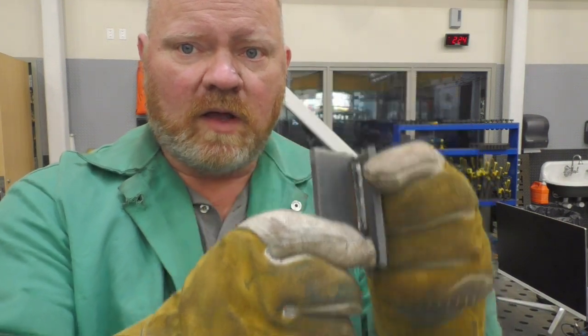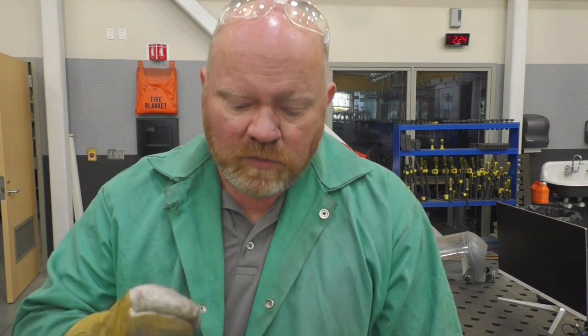And again, I also tested this on a very small weld. That's a really small weld, about an 1/8 inch fillet weld, okay? So if you're gonna plan on putting down larger welds, multiple pass or whatever, the root pass is the key. So kind of closing up, I'll finish this one off here. We won't be too long.